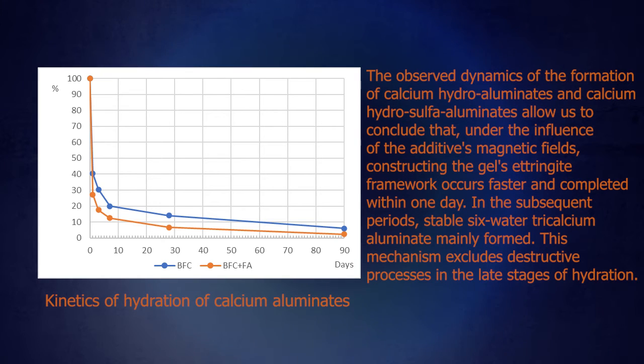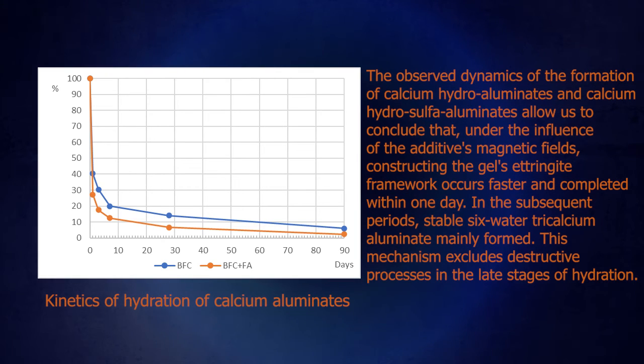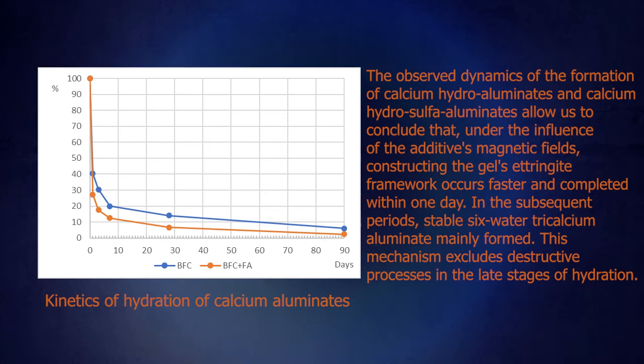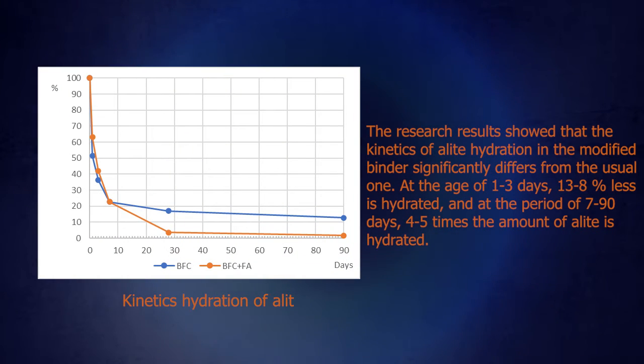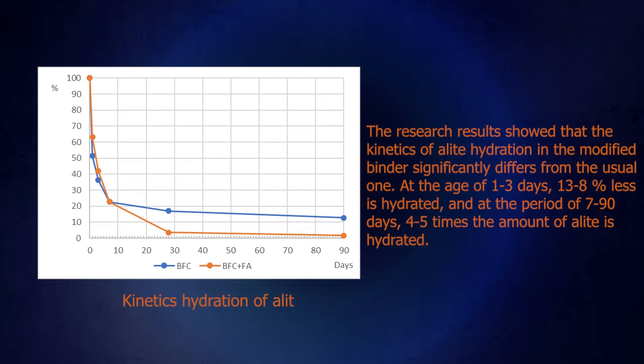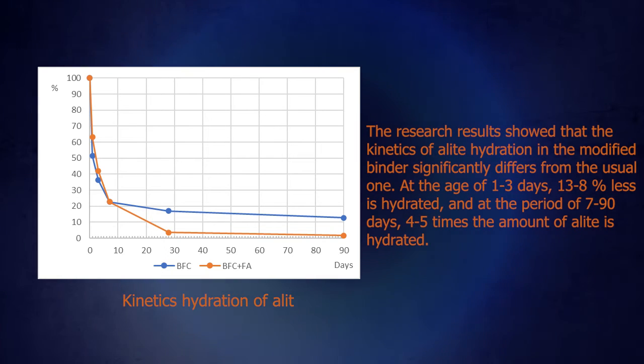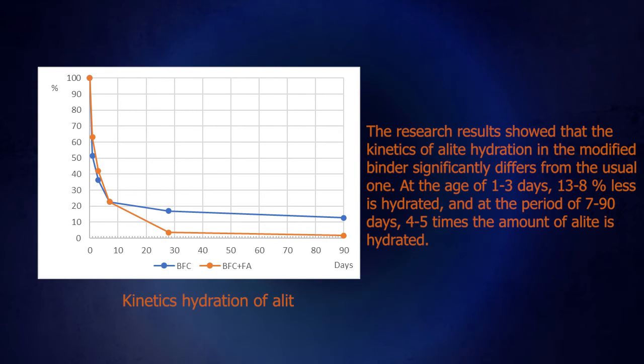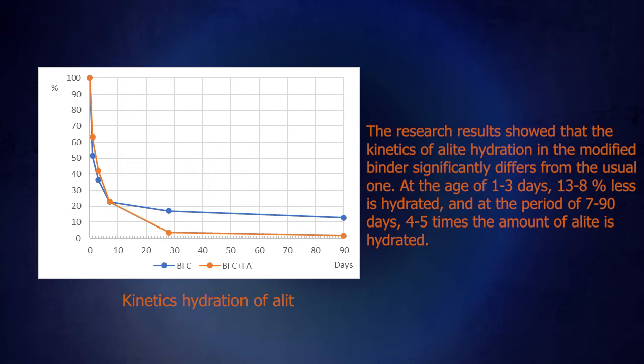In the subsequent periods, stable 6-water tricalcium aluminate is mainly formed. This mechanism excludes destructive processes in the late stages of hydration. The research results showed that the kinetics of alite hydration in the modified binders significantly differs from the usual one. At the age of 1 to 3 days, 13-8% less is hydrated, and at the period of 7 to 90 days, 4-5 times the amount of alite is hydrated.